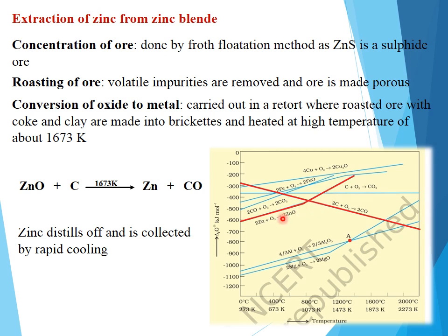Whereas below that temperature they are lying above, and above that temperature these carbon graphs will be lying below the zinc graph. Hence coke can be used as a reducing agent to reduce zinc oxide to zinc metal. So this is the way we select and use coke as a reducing agent in the extraction of zinc from zinc oxide.